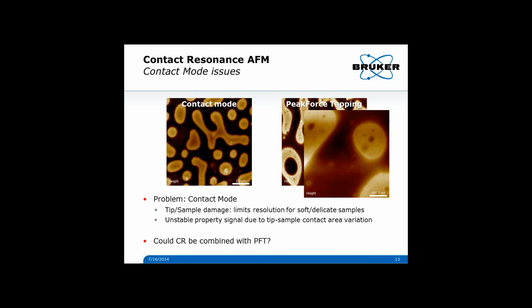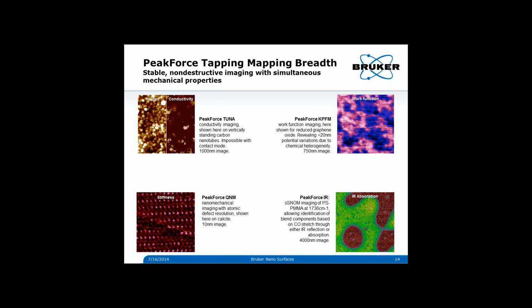So the question arises, could contact resonance be combined with peak force tapping? We've combined it in several cases previously. We have this peak force TUNA mode. This is a map with conductivity and height showing vertically standing carbon nanotubes, which definitely would be impossible in contact mode. Here's a peak force KPFM map where we analyzed the work function around a sample. You can also get very high resolution stiffness maps down to the atomic level, or now with this Inspire, peak force IR, we can get an IR absorption or reflection map. This is a PS-PMMA sample again.